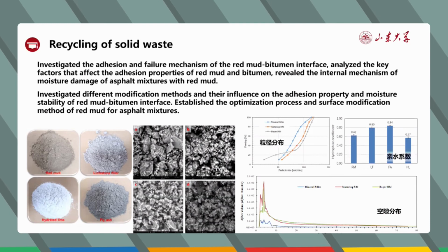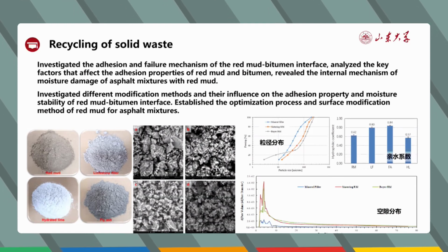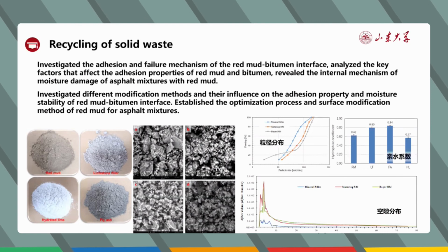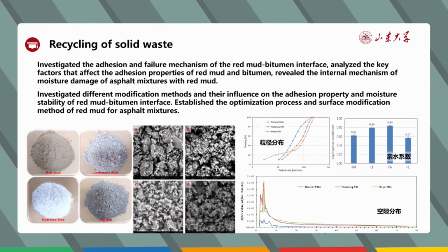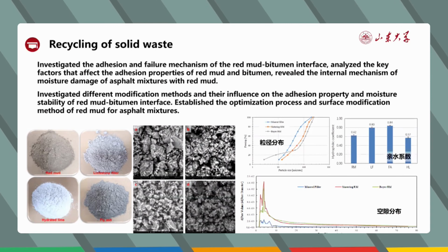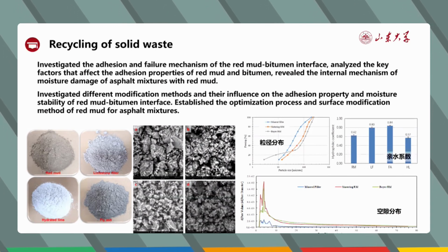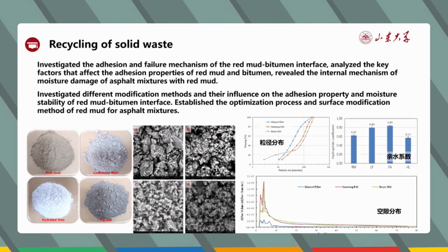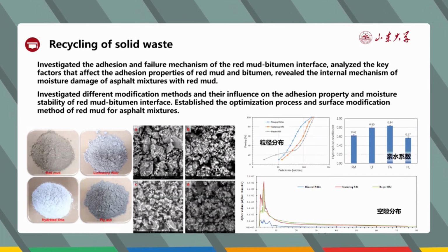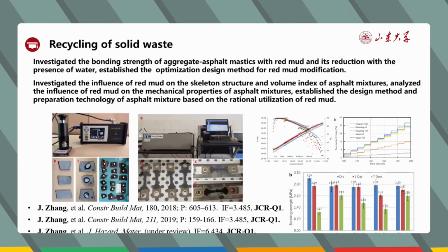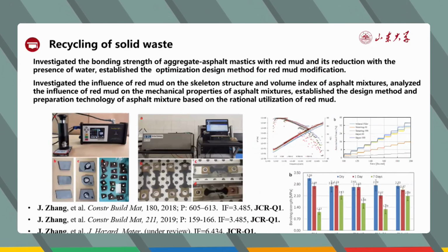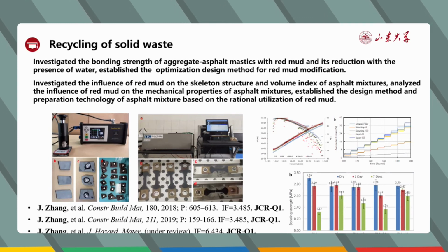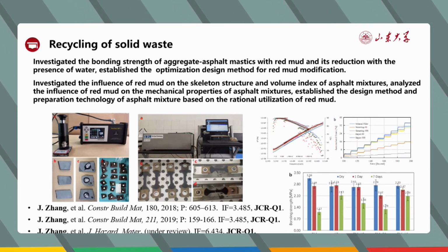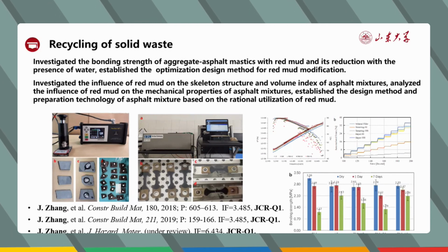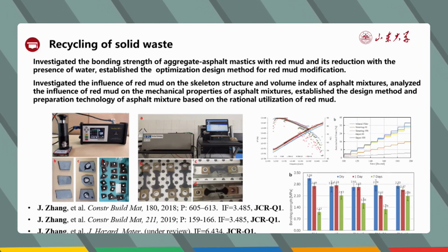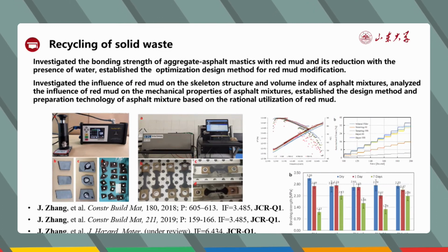We also investigated different modification methods and their influence on the adhesion properties and moisture stability of the red mud bitumen interface. We also established the optimization process and the surface modification method of red mud for asphalt mixtures. We also investigated the bonding strengths of aggregate asphalt mastic with red mud and its reduction with the presence of water. We also established the optimization design method for red mud modification.